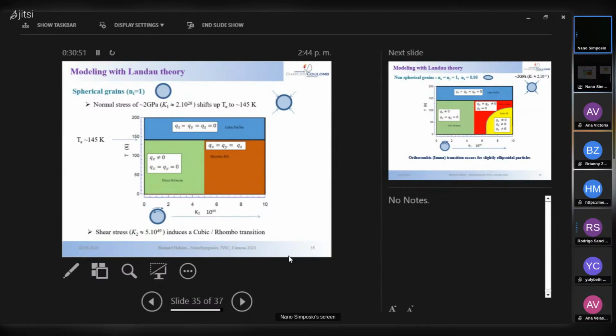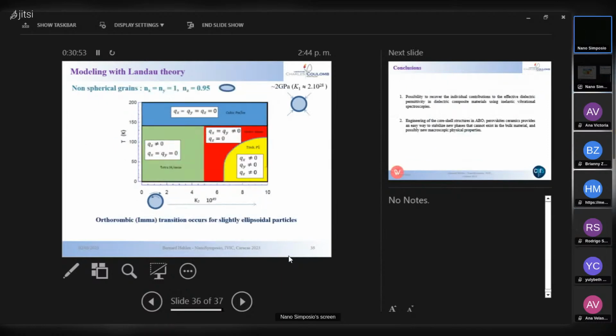So what we did now is we consider that the grains are not spherical anymore, but ellipsoid. Very weakly ellipsoid. You see there is 0.95, 5% ellipsoidicity along the z-axis. And if you do that, you see that you apply a shear stress here, still at 2 gigapascal of uniaxial pressure. But if you apply now a shear stress, now you induce an orthorhombic phase. Exactly what you found experimentally.